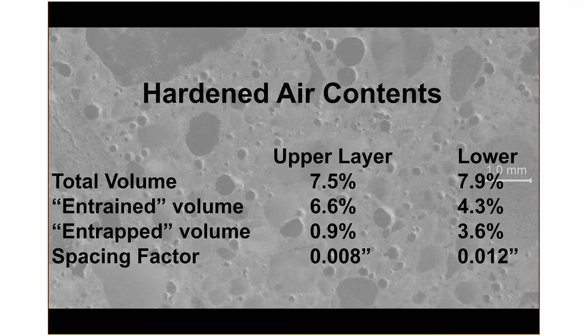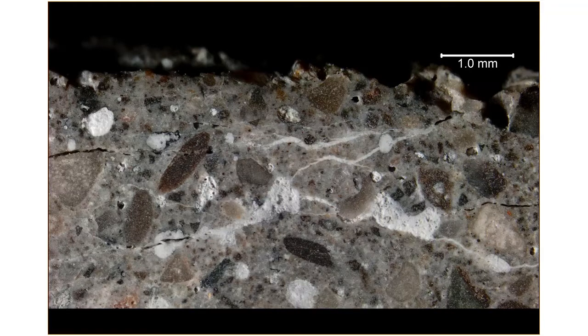All right. Some other interesting petrographic anomalies that were noted in this concrete. Now, very interesting image, and we can see a lot of sub-horizontal cracks. This is taken right at the top surface of this pavement, under fairly high magnification here, probably 20, 30 times magnification. Note those white secondary deposit filled subhorizontal microcracks. And you see a number of void spaces that are filled with white secondary deposits.